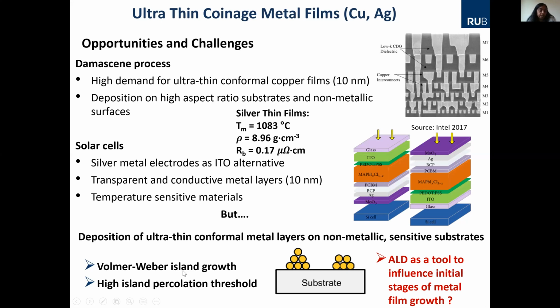And that is a challenge, because the mechanism that is known during the deposition of metal layers is actually dictated by Vollmer-Weber island growth. That means you have certain islands formed, they join together, and then you have a percolation. That means you have a continuous film, but you end up in thicker layers which are not transparent but maybe conducting. But now you want to have thinner coatings which are transparent and conducting. And that's the challenge. You're talking about 10 nanometers. So copper has been always a headache.